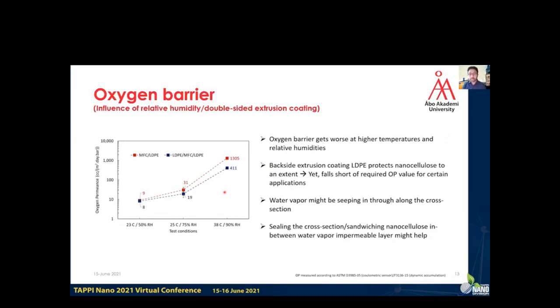This is because water vapor might be seeping in along the cross section. Sealing the cross section or sandwiching nanocellulose in between water impermeable layers might help improve the barrier a little bit, but still it is promising that a backside coating of LDPE protects the nanocellulose layer to an extent.